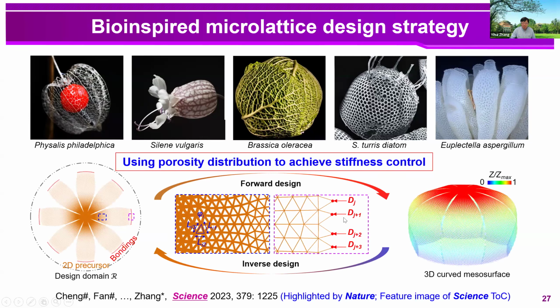And by using this kind of microlattice design, we can bypass the technical challenges in the gradient thickness control. Because based on the microfabrication techniques, we can easily control the width distribution in the 2D structure. And the smallest width we can achieve is around several tens of nanometers.